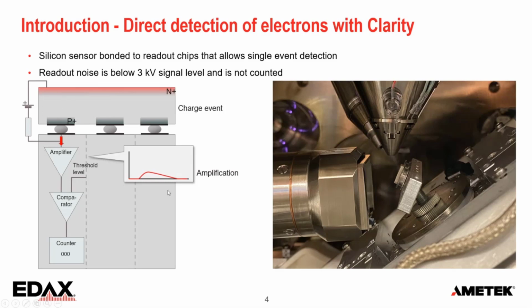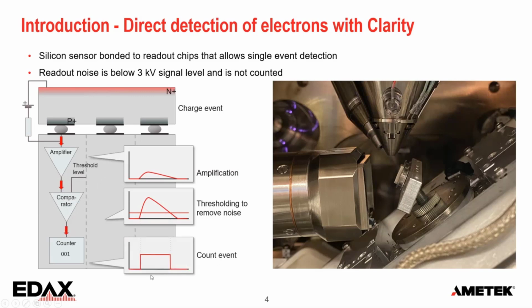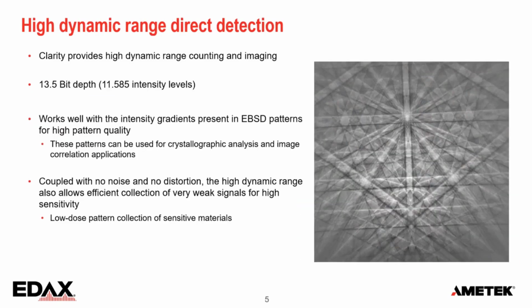And the signal goes into an amplifier. Then comparator, so we just see what is real, what's not real. So we're going to remove all the noise that we have in the system. And this read noise actually is below 3 keV. So there's virtually no noise at all in the system once we've gone through this step. And after that, we can count an event. So effectively, we can count single electrons coming in. So we can quantify the signal that is coming in. And the detector itself has a very large bit depth. So as I say here, 13.5, it's about 11,500 intensity levels.